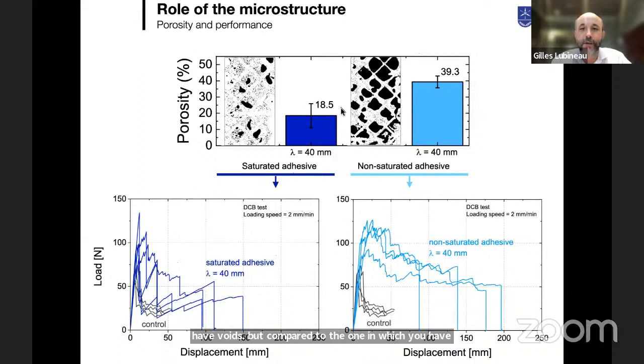And sometimes, for example in this technology, you want to have porosities. You want to have voids because voids are a way to introduce a porous structure that is going to dissipate a lot of energy. If you want to avoid voids, that is what you do in classical composites. The only way is first to be very careful when you make your co-bonding so that you don't trap air inside, and then you go with the classical vacuum plus pressure systems to make sure that you can suck out the air.